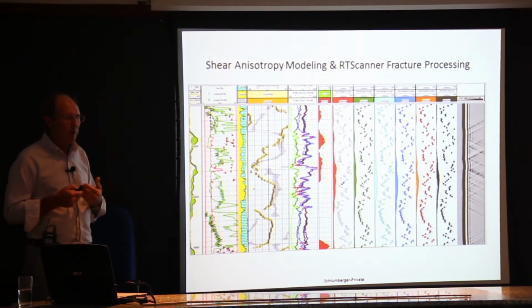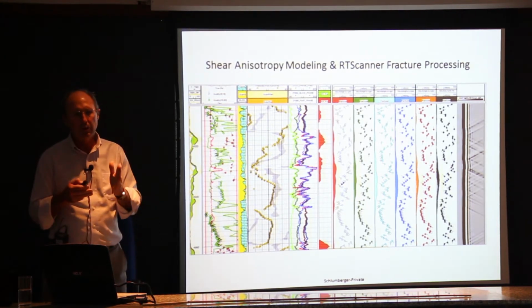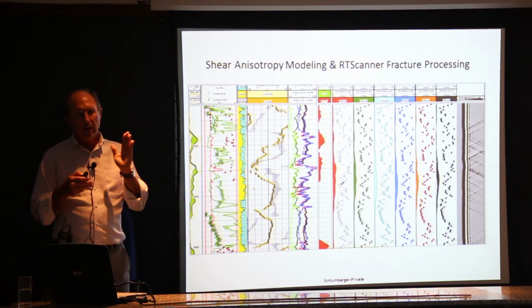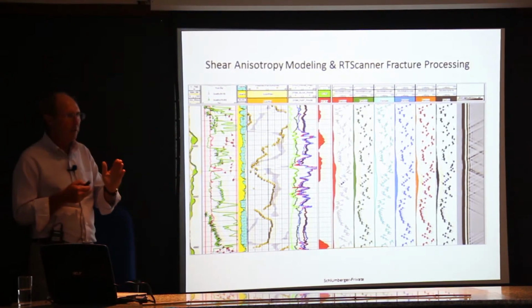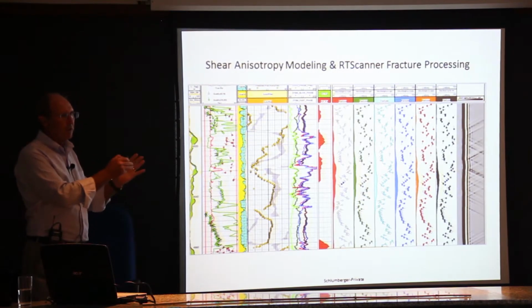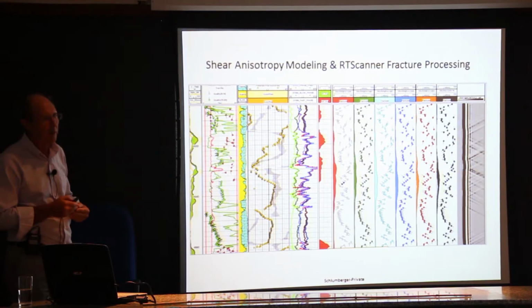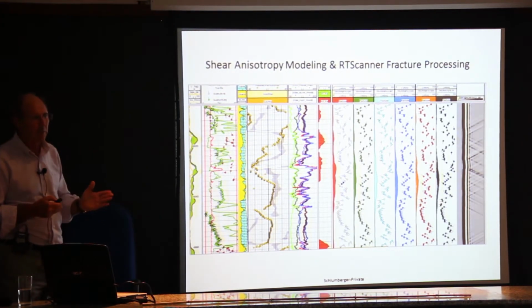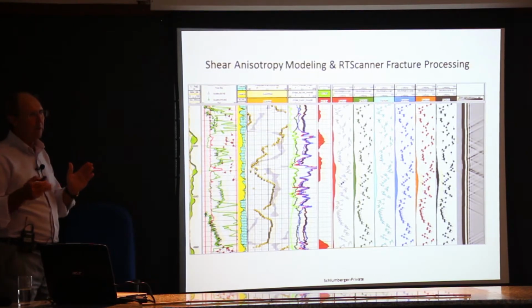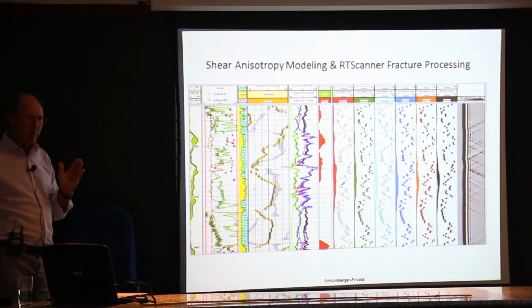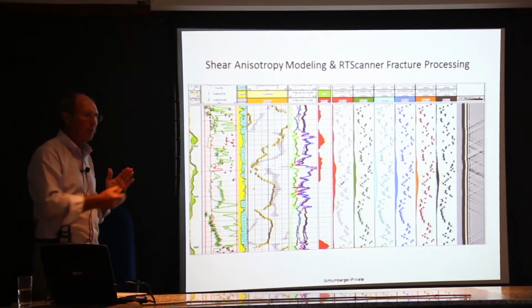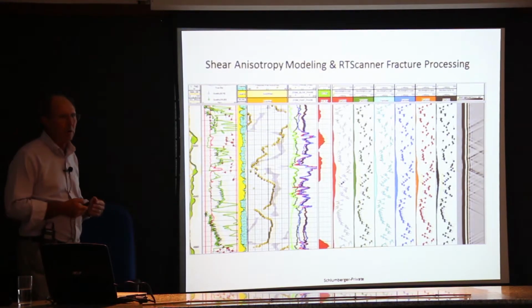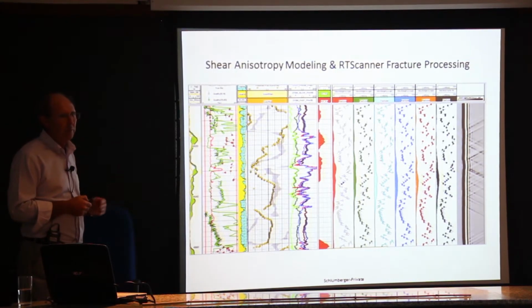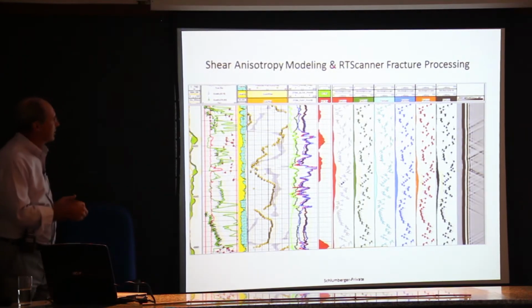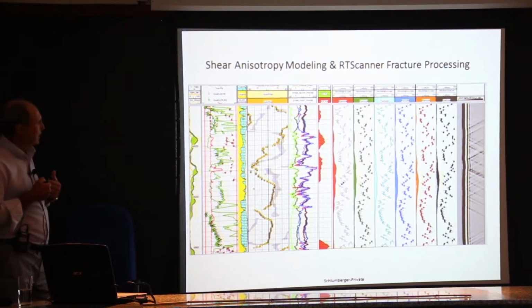So this is a big step forward in terms of multi-physics and geophysics for pre-salt evaluation, where you look at anisotropy in terms of electrical and acoustic terms to try to resolve these shallow drilling-induced fractures from the deeper natural fractures. The deeper natural fractures will have a big impact on production, but they'll also have a potentially big impact once you start water injection. If you get water injected into these fractured networks, you can get water breakthrough extremely quickly and make the well maybe uneconomic. So it's very important to map these fracture corridors, and this is a big step forward in terms of both the sensors from a physics perspective, but also the processing as well.